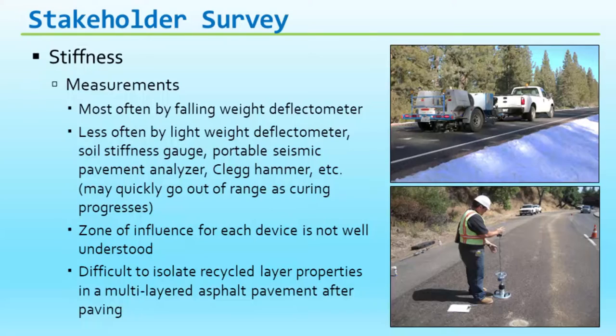California also has a wet density test that they do in the field. We're seeing some major problems with that because it was developed for subgrade and base materials. There is some correlation to stiffness, but unfortunately it's only a snapshot. It doesn't give us a change in stiffness over time, which we are experiencing with traffic. So again, those measurements for stiffness, if it's for long-term performance, the agencies that are doing it with a falling weight deflectometer. Unfortunately, not a lot of measurements over time.